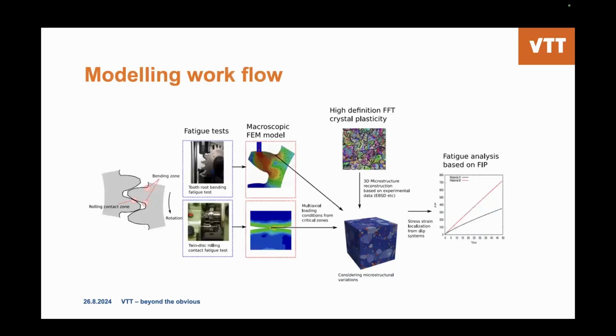So to gain a deeper understanding of the microstructural links between the macro fatigue performance and the microstructures, we have established this multi-scale modeling workflow. Firstly, macroscopic finite element models for both tooth root bending fatigue tests and twin disc rolling contact fatigue have been performed. And we extract the multi-axial loading conditions from the critical area for both cases and apply them to the virtual microstructure as boundary conditions. The virtual microstructure is highly statistically representative. I would say it's made from experimental data like EBSD.